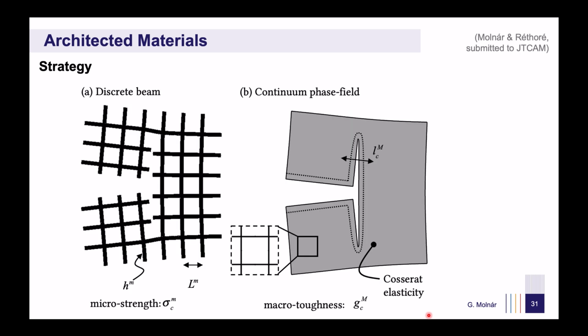This leads us to an important question. If the representative volume element contains all relevant mechanical properties, could we determine its fracture toughness and create a homogeneous phase field model? This phase field model should fail at the same critical load as the lattice and reproduce the crack patterns observed in the microstructure across different loading conditions.